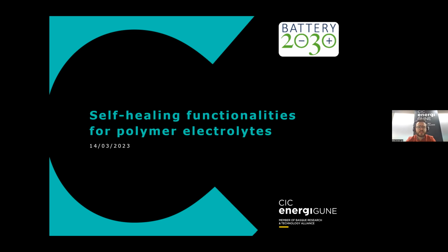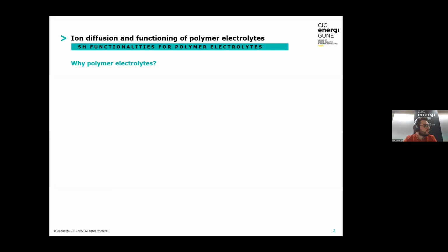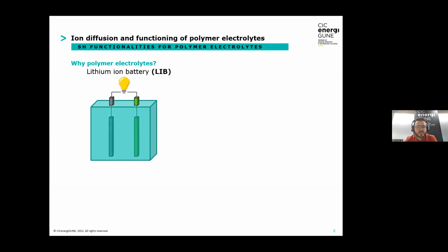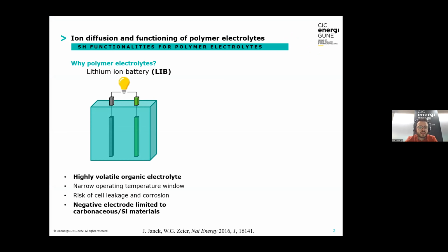Currently in lithium-ion batteries, we are using organic liquid electrolytes, which are highly volatile and narrow the operating temperature window of the batteries, and most importantly, they limit the negative electrode to carbon or carbon-silicon materials, as we've seen in the last presentation. This limitation comes mainly since the use of lithium metal negative electrodes leads to the formation of lithium dendrites, which pose a risk for the battery, since they might lead to cell short circuit, thermal runaway, and at the end the risk of fire or explosion of the battery. Also, the inability to use lithium metal electrodes leads to a lower energy density in the battery.